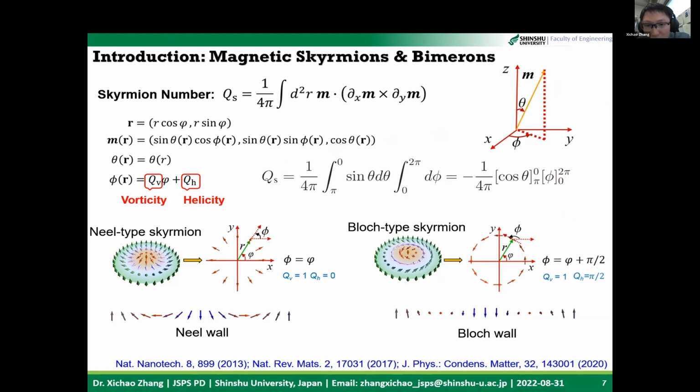I think you mean the system with heavy metal is a system such as a multilayer or materials prepared by magnetron sputtering. But in some bulk chiral magnets, you can have the DMI due to the broken inversion symmetry of the materials. I'm not sure about the insulator because I only work on simulations. Maybe you can ask an experimental researcher about this question.